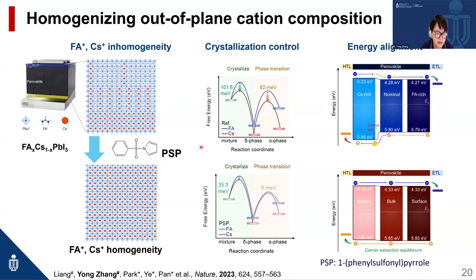Here we try to introduce PSP as an additive in this FA-cesium mixed perovskite. We found that PSP can control the crystallization rate of FA and cesium perovskite, making the homogeneity of the perovskite film in the out-of-plane direction. Then we can achieve efficient charge transport.